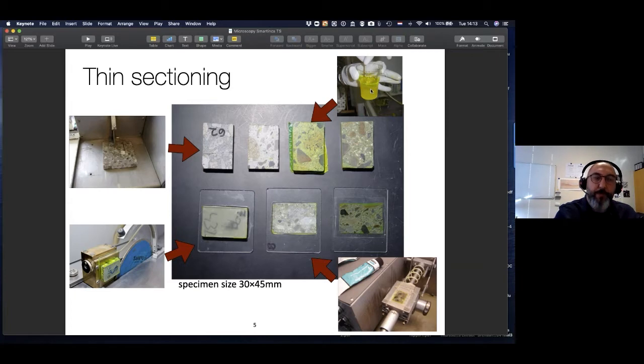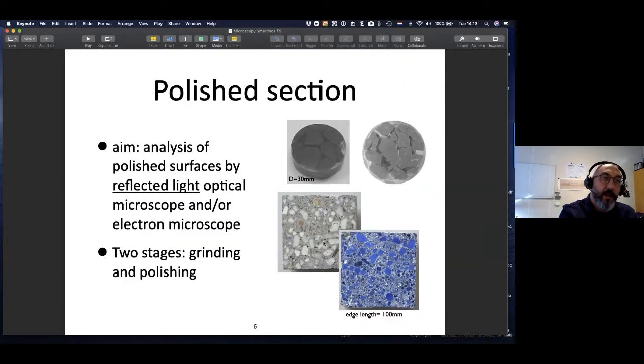And we impregnate our porous concrete to make it really robust and strong during all this cutting, chopping, and grinding operation. And finally, again, with these machines, we achieve a 30 micrometer thickness. Polished sectioning is relatively less labor intensive, but it's still very serious business.